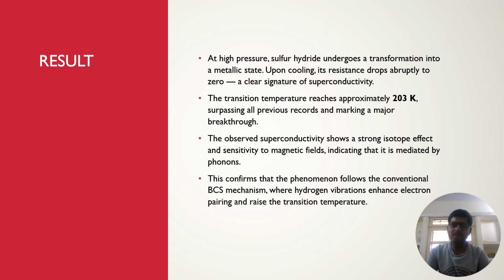The superconducting state is also suppressed by magnetic fields, which is consistent with the breaking of Cooper pairs. Together, these results confirm that superconductivity in this system follows the conventional BCS mechanism. However, despite these promising results, there are some limitations also.